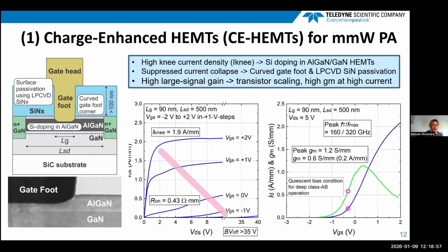And we have the curved gate foot corner, as you can see below in the TEM images. And this structure alleviates the peaked electric field at the drain end of the gate without use of the nano field plate. And then we use surface passivation using LPCVD silicon nitride to minimize the surface trapping effect.